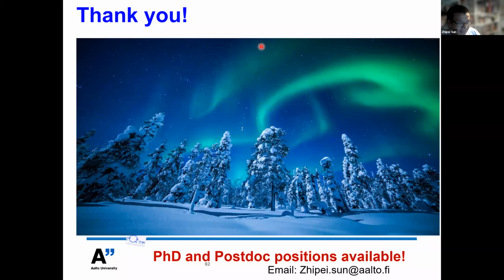Thanks for this question, which is really nice, because at the moment I have to agree that we don't have a huge control over a lot of these extrinsic factors. For example, even with mechanically exfoliated flakes, we can always find defects. We still could find a lot of defects on the surface. This is something we cannot easily control, but if we fabricate devices like I mentioned, with different flakes using a similar method, we could compare the methods in a pretty fair way to exclude these extrinsic factors in the measurement.